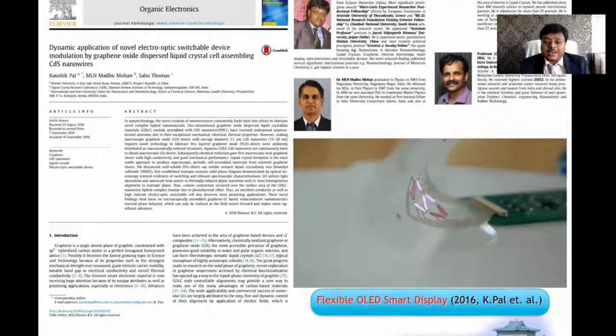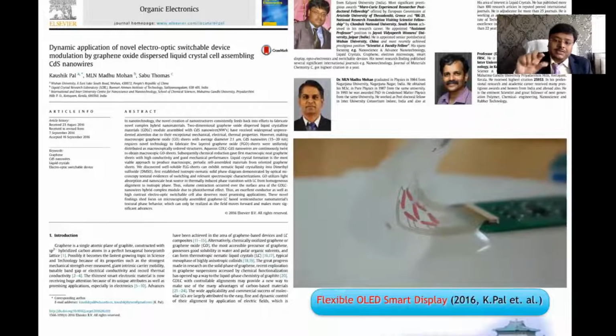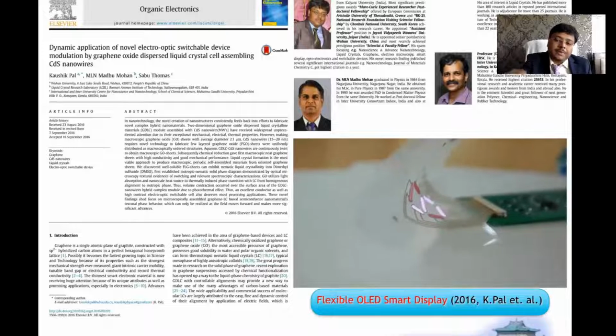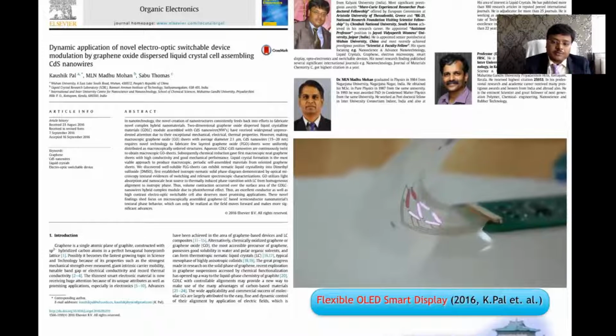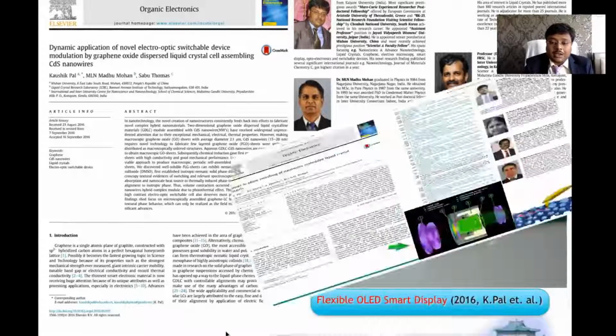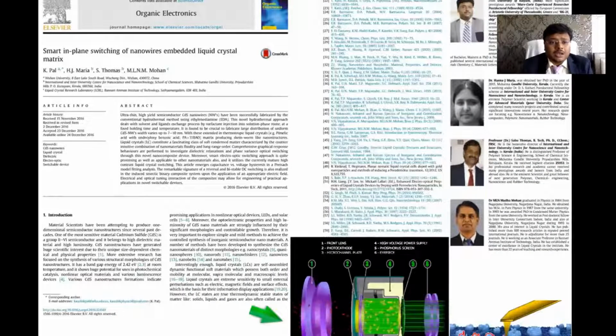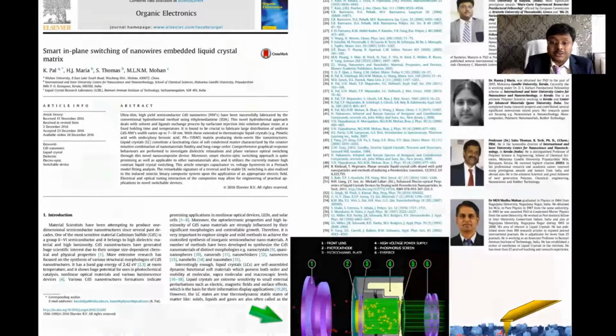So here we can see the flexible film we used, the electrode frames we used, and you can see how it is working. And this is our smart in-plane switching of nanowires embedded liquid crystal matrix. The same things, but a different material we used here. And we measured the surface current, and through AFM you can see the surface current. We measured this through these experiments.